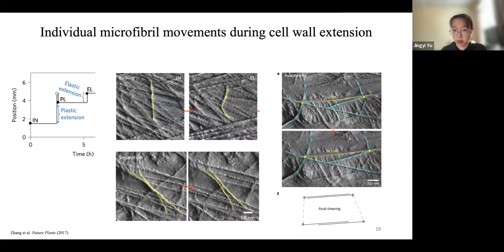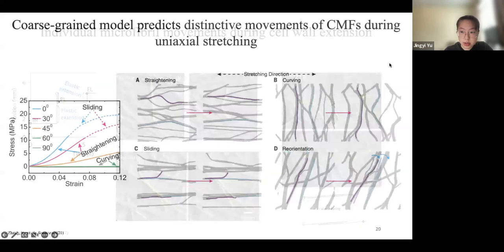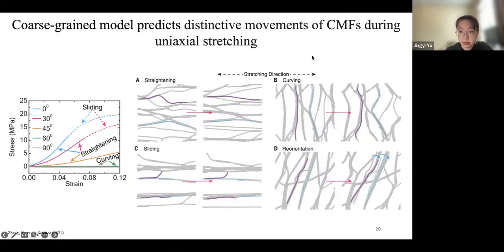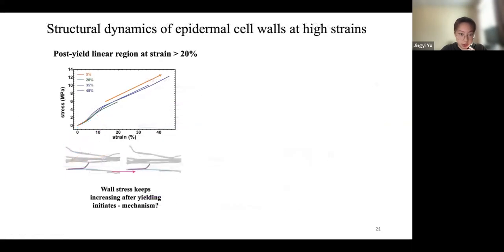Previous studies from our lab have observed some individual microfibril movements during cell wall extension, where we were able to stretch the cell wall under atomic force microscopy and observe behaviors such as kinking, separation, and shearing of fibers, which is similar to the sliding I mentioned in the previous slides. Following that, we also developed a coarse-grain model that is able to predict distinct movements of cellulose microfibrils under uniaxial stretching, where we see the straightening and sliding of fiber lines towards the stretching direction, as well as curving and reorientation for fibers that passively accommodate the overall dimensional change of the cell wall. Both of these observations characterize the cell wall mechanics and the underlying molecular mechanisms, from the elastic region to the initiation of plastic deformation.